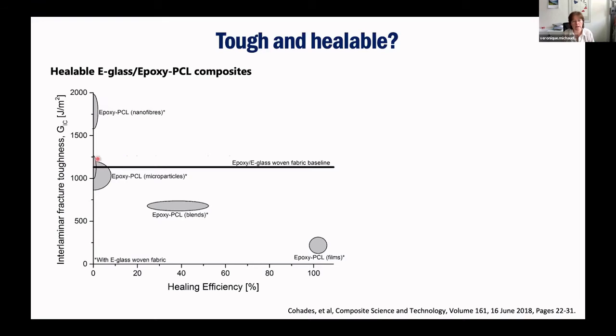We also tried, this is the baseline epoxy we had. So around here, we tried also PCL microparticles and whatever, and nothing worked in terms of healing. The only healing we could get was either with the blends, as we did, or with just taking PCL interlayers, so in between the composite. That was a great healing efficiency, of course, but zero or very low interlaminar fracture toughness, because we really weakened the material.